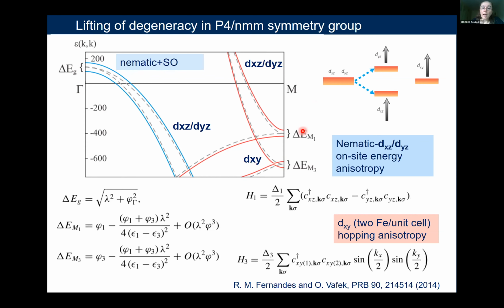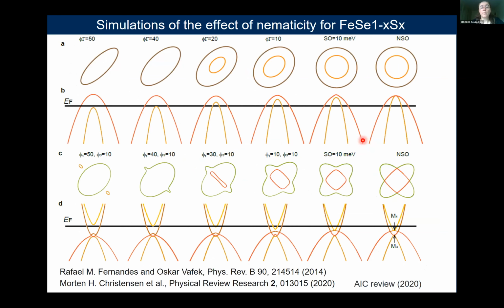And then for the electron bands, the effects are even more dramatic because besides lifting the degeneracies of XZ and YZ band, we have further anisotropy to do with the dxy orbital and their hopping anisotropy. And they will cause extra shifts. These points are supposed to be degenerate in the tetragonal phase, but turning these effects on, the bands will shift in an unusual way. And these are some simulation of how these effects might occur.